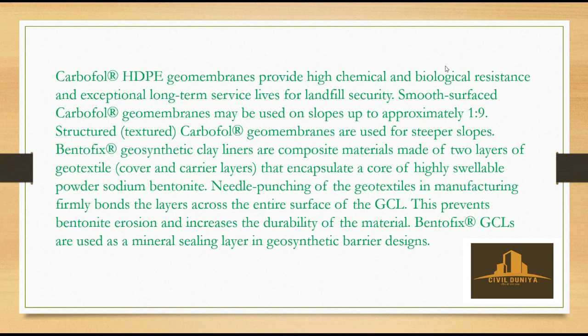Carbofol HDPE geomembranes provide high chemical and biological resistance and exceptional long-term service lives for landfill security. Smooth-surfaced Carbofol geomembranes may be used on slopes up to approximately 1 to 9. Textured Carbofol geomembranes are used for steeper slopes. Bentofix geosynthetic clay liners are composite materials made of two layers of geotextile — cover and carrier layers — that encapsulate a core of highly swellable powder sodium bentonite. Needle punching of the geotextiles in manufacturing firmly bonds the layers across the entire surface of the GCL.